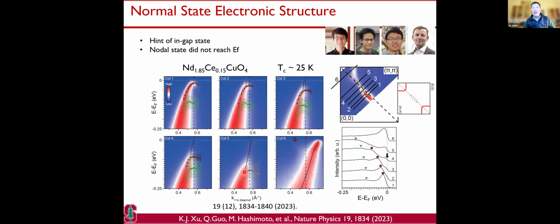You can see that this main feature is being gapped dramatically. That's sort of this kind of band, the red feature. Okay. Then when you cut number 6, the antinode, you again see a very strong band, and this band crosses the Fermi level. You can see there's a discontinuous jump between 5 and 6.